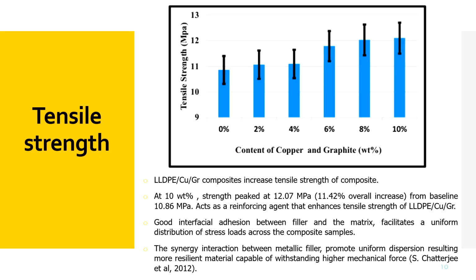In terms of tensile strength, as we can see, the addition of the hybrid copper and graphite from 2 to 10% resulted in an increase in the tensile strength. So this means that the mechanical properties of the main matrix, LLDPE, are improved.